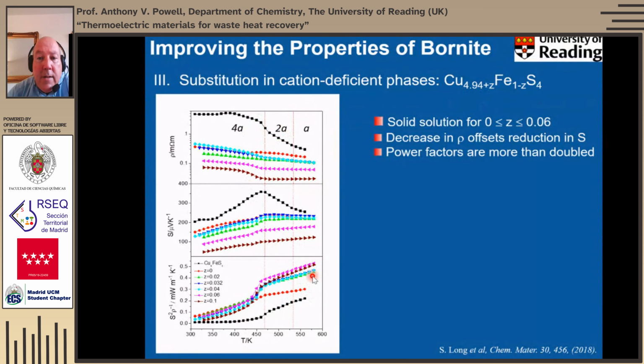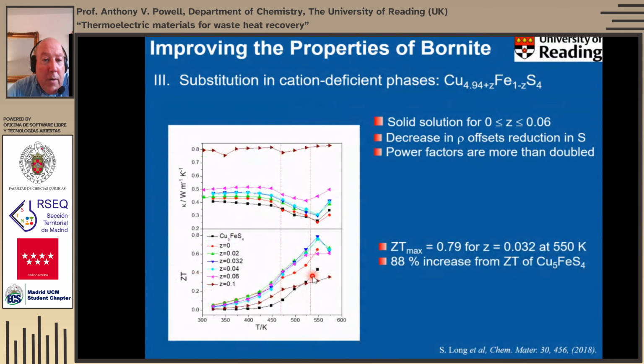in power factors. Power factors are more than doubled here. And then we look at the thermal conductivity. We find that it does increase, but we're not impacting on the thermal conductivity quite as much as we were in those other series. And I think that's probably because of the vacancies. And we reach a ZT maximum that's almost 0.8, 0.79, at a very low temperature of 550 Kelvin. So this is actually one of the best performing materials in this industrial waste heat region.